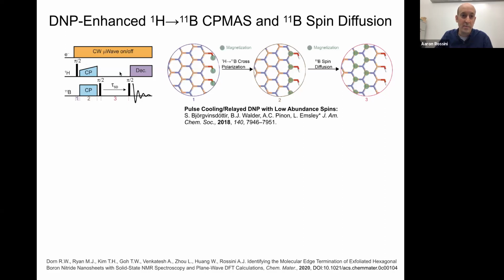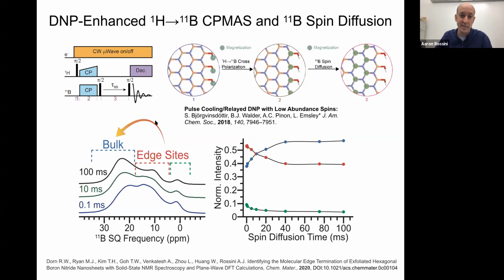So here we use DNP to enhance the proton magnetization of the edge protons. We transfer that DNP enhanced magnetization to the edge borons using a cross-polarization step. And then we give it some time for spin diffusion and can watch the boron magnetization diffuse into the bulk if these are the edge sites. And that's exactly what we see happening. When we have a short spin diffusion time of 0.1 milliseconds, we more or less see that edge selective NMR spectrum. And then as we increase the spin diffusion delay, we can see the magnetization entering into the bulk and giving us those bulk-like NMR signals.